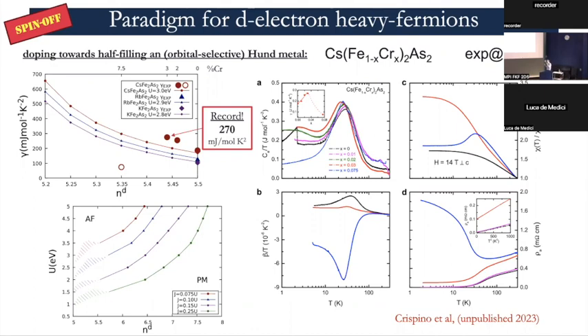So the take-home message here is that by dynamically generating these heavy electrons, when you take a Hund's metal and you move towards half-filling, Hund's metals tend to be selective, and this selectivity can be extremized. And just before everything is cut off by magnetism, you can have a heavy fermion, and possibly you can go even up to the ballpark of Sommerfeld coefficients typical of heavy fermions. And then some different but very similar physics comes when you include non-local correlation, and this is related to the talk of Jan van Telft that he gave two days ago.